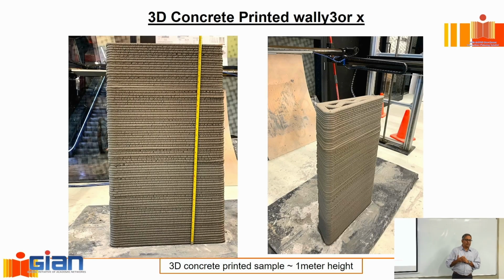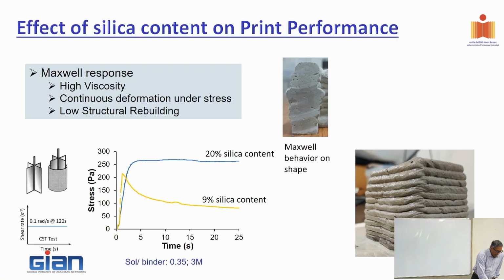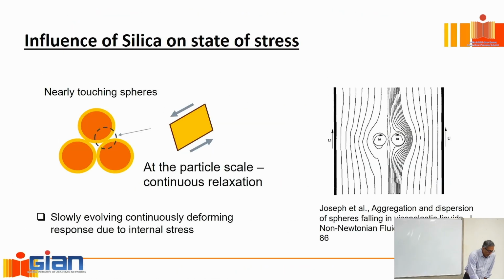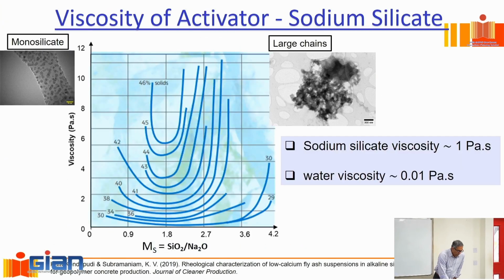We'll have to learn to deal with all the tricks that silica is going to throw at you. Silica will make the solution viscous, period. We are reducing the particle size. Yes. So if you look at the sodium silicate viscosity graph, I think you probably missed it. So this is the graph of sodium silicate and viscosity. This is the MS, the silica to sodium ratio.